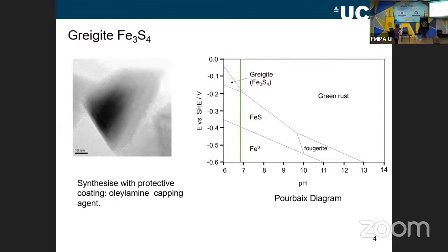The important thing here is that greigite is actually only stable in this tiny region here. So this diagram is telling me that if I go to a higher pH, greigite should change into green rust, which is an iron oxide material. And if I go down to lower potentials, if I reduce it, it should change to FeS and then eventually to metallic iron. So the capping agent, we're hoping, will keep it stable a bit longer so it doesn't immediately just turn into rust, into oxide.